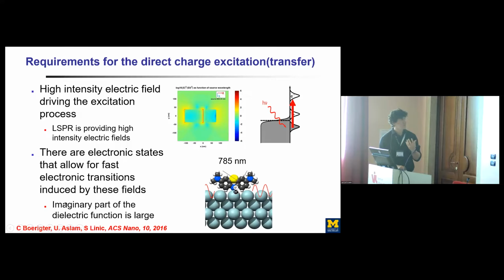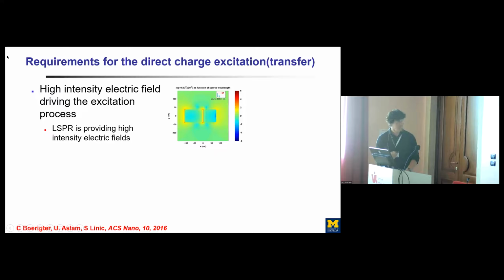And that means that you have electronic states that allow for fast electronic transitions that are driven by these fields. And in practical terms, it means that you have to have something that has a very large imaginary part of the dielectric function. So now if you marry that something with a plasmonic nanoparticle, you should be able to selectively drive energy into that something that has a larger imaginary part of the dielectric function. When you think about this, it's really not that surprising. You put energy in the system, and it's going to go down the path of low resistance, and that's provided by these electronic states that allow for fast optical excitations.